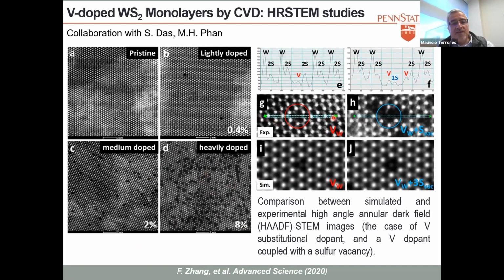So when you do a line scan here, you can see the vanadium atom is there. Very low intensity, and here you have two vanadiums, one here, one there, and then you have one sulfur vacancy here. So we can see these defects by electron microscopy, and then we can have an idea of the density of these dopants. So this is important because putting this large amount of vanadium into the system, it's very complicated. It's very difficult. I think maybe we're the first ones to achieve 8%, and we can go to 12%.